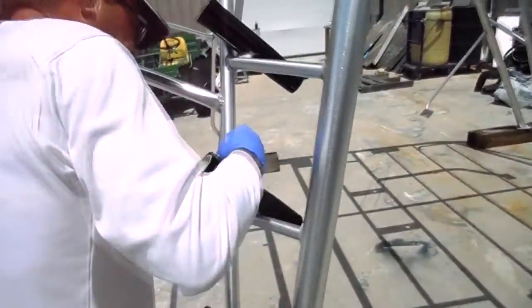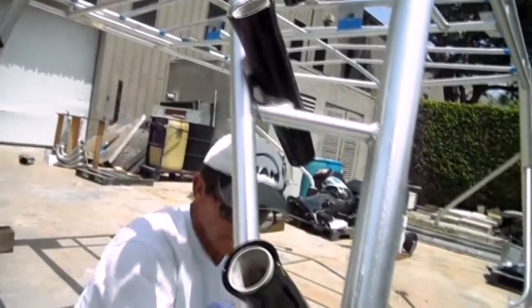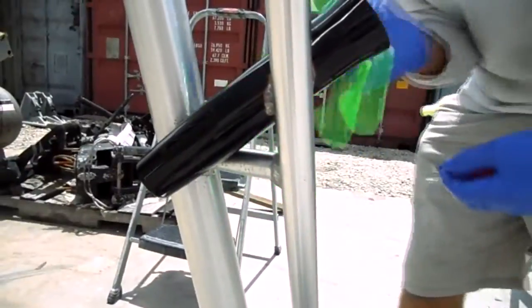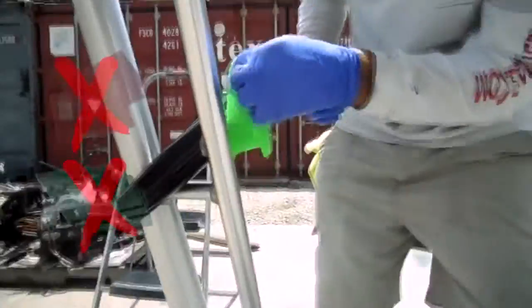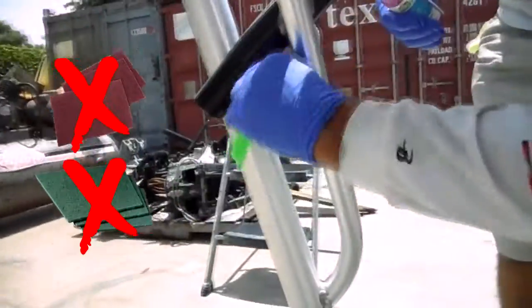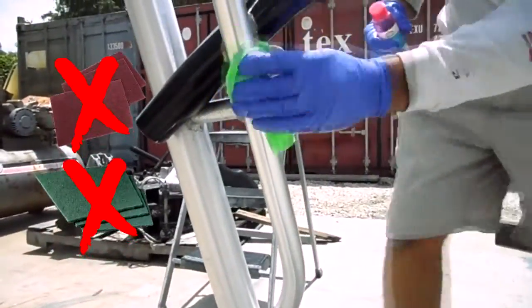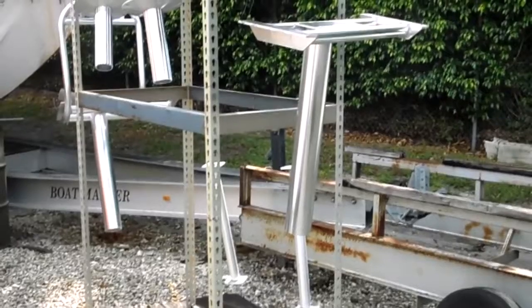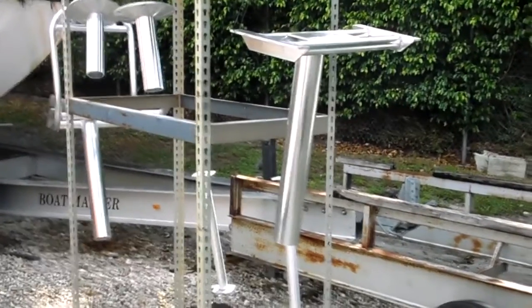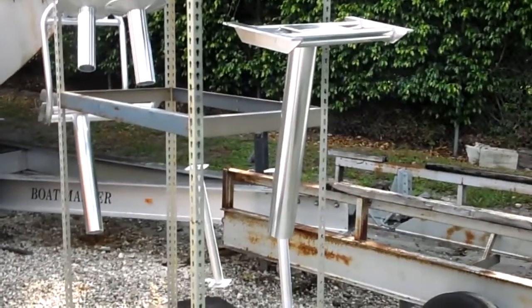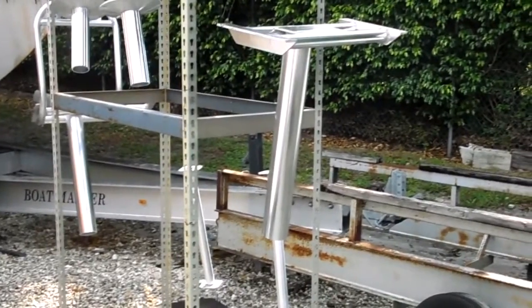SB230 becomes tack-free after 60 minutes, dries in 24 hours, and takes 5 days to fully cure. Once fully cured, the only upkeep it will ever require is mild soap and water. You don't want to use any abrasives to clean the metal, as the coating could be damaged. The same procedure is applied to our foot pedestals and seat mounts, creating a uniform look across the entire boat.